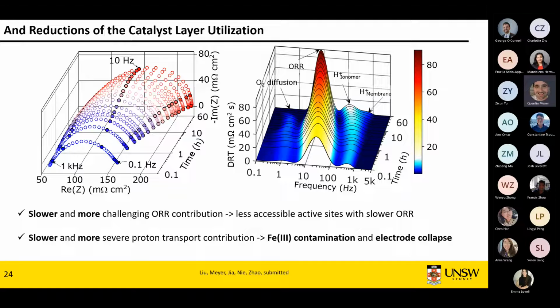What's a bit interesting, and we're still looking into it, is you can see that the mass transport peak initially is quite large, and then becomes smaller and smaller, and eventually is completely gone. So one likely reason is that your catalyst layer is collapsing, but because it was so thick initially, it becomes thinner. You just have easier gas diffusion overall through it. Even if you still have a lot of problems, overall you don't have that one problem anymore. That's probably a bad thing because it happens because the carbon has completely corroded. So this gives you quite a good overview of what's happening.